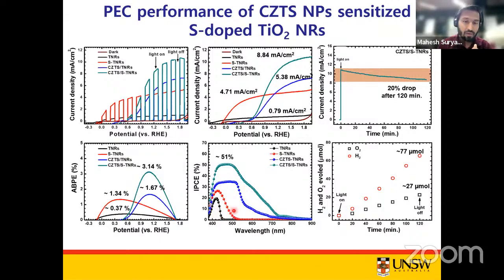Sulfur doping, however, is limited only up to 500 nanometers. That's because the reduction in the band gap is not that high. And again, as a synergistic influence of CZTS sensitization and the sulfur doping into TiO2 nanorod arrays, the IPCE values and the photoactivity over a broad range were also significantly enhanced.